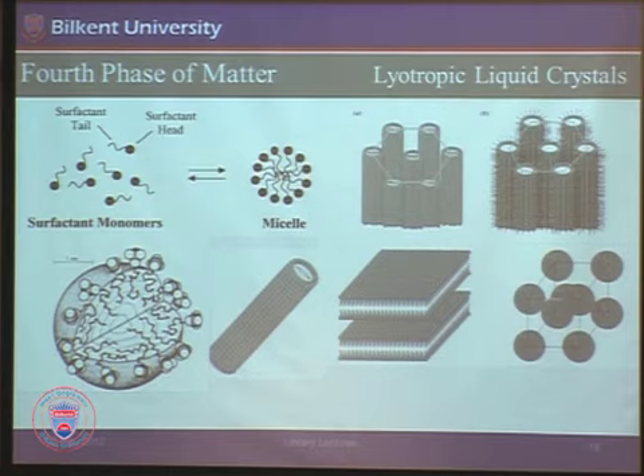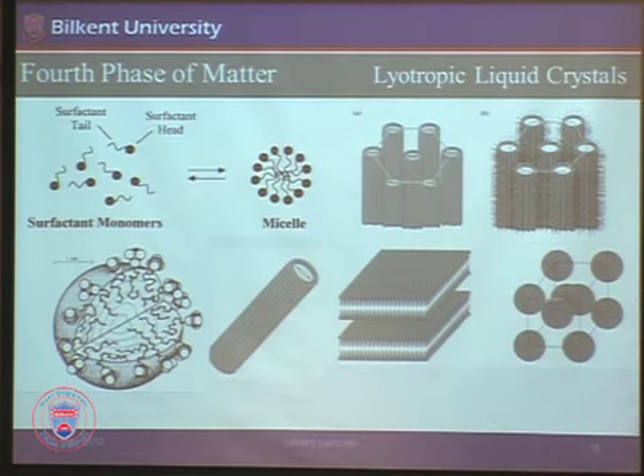These rods are made up of those surfactant molecules. They self-assemble together to form these rod-like micelles, and these rod-like micelles come together to form this liquid crystalline phase. Okay? And here, in between these rods, you have the water, in this example, water molecules. You can do a lot of chemistry there. In this tiny space, a few nanometer space, you can do chemistry.